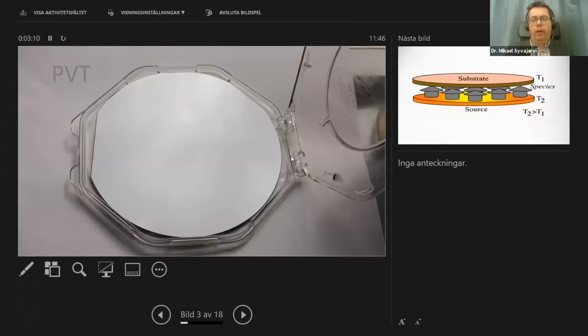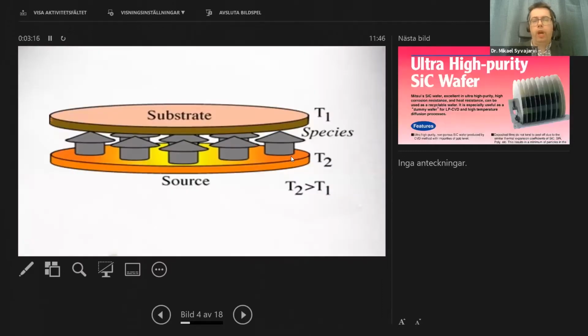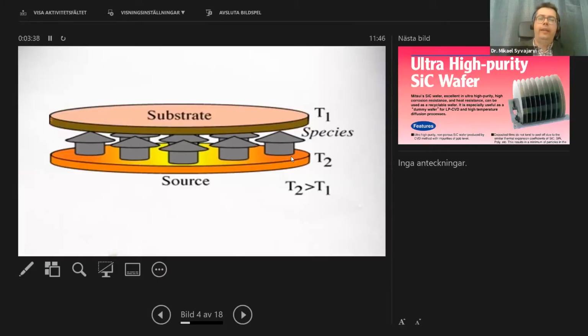And my particular focus in growth of silicon carbide was to modify this method and change the conditions so we had a smaller distance for the transport of material. So then we cannot grow large bulk type material for wafers, but we could grow thick layers. And then the idea was that that is interesting for the power devices, because then you need thick layers to transform 10,000 volts and so on.